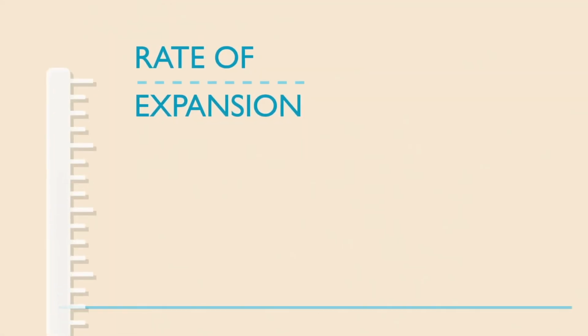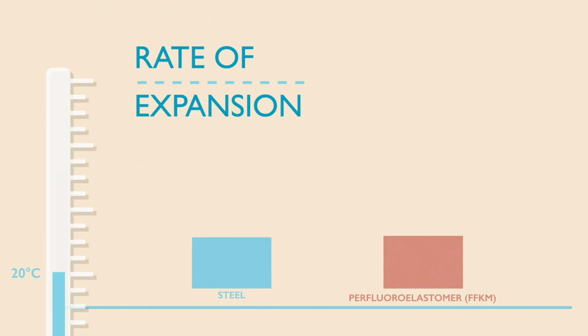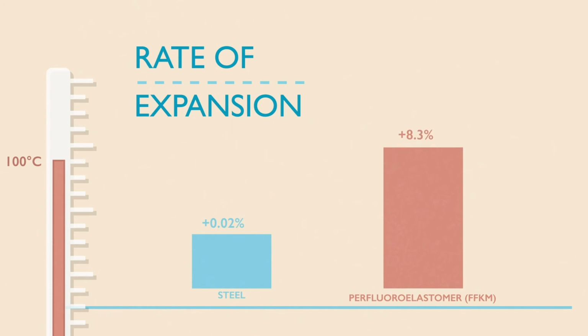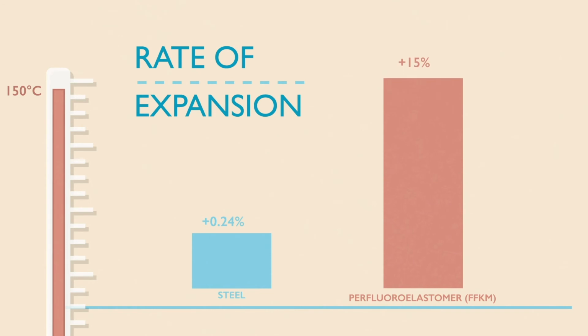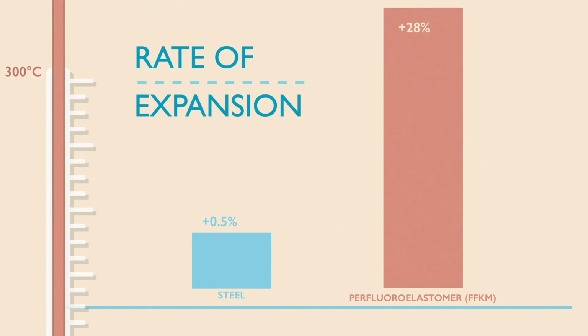Let's now compare the rate of expansion for steel and perfluoroelastomer, FFKM, using two samples of the same size at 20 degrees Celsius. As the temperature increases to 50 degrees Celsius, the perfluoroelastomer is starting to expand by 3% compared to the steel, which has barely changed. At 100 degrees Celsius, the perfluoroelastomer has expanded by 8.3%, and the steel has changed very little. When the temperature reaches 150 degrees Celsius, the perfluoroelastomer has expanded in volume by 15%, while the steel is still relatively unchanged. If the temperature continued increasing, the perfluoroelastomer's rate of expansion will continue to be much greater than the steel. At 300 degrees Celsius, the perfluoroelastomer has expanded by 28%, and the steel only 0.5%.